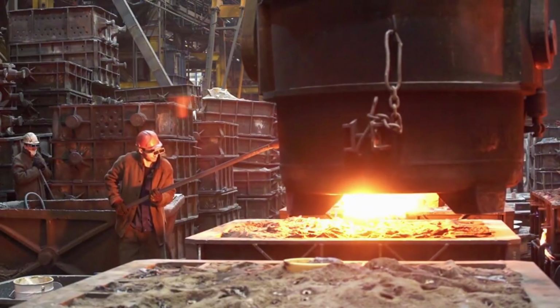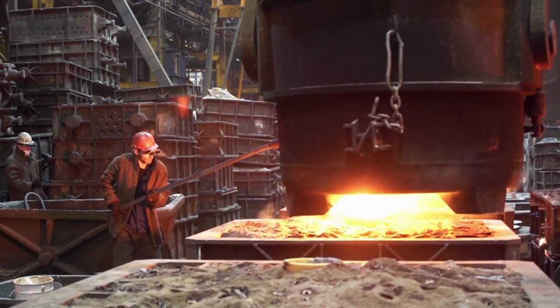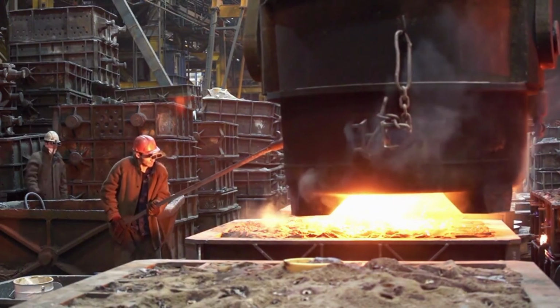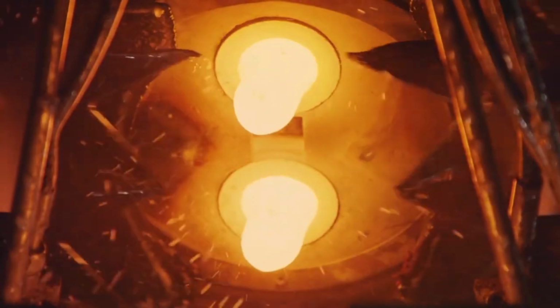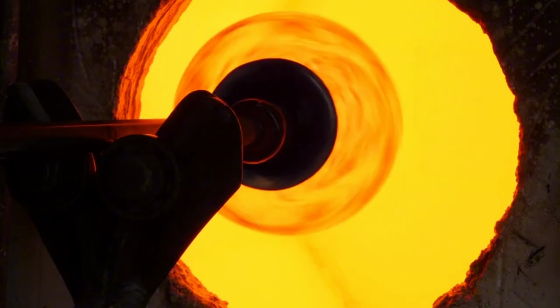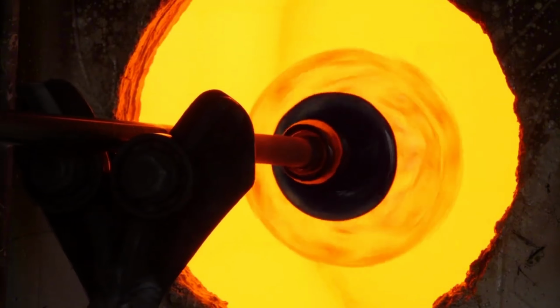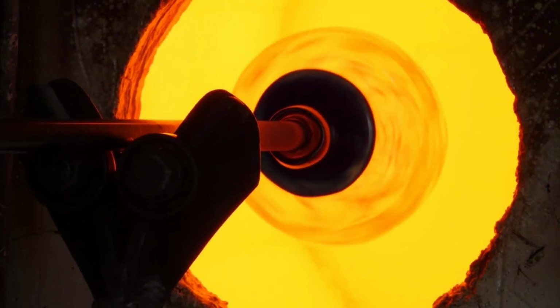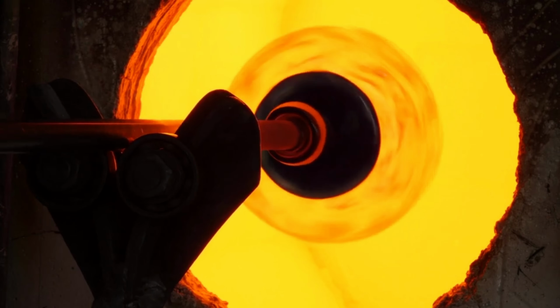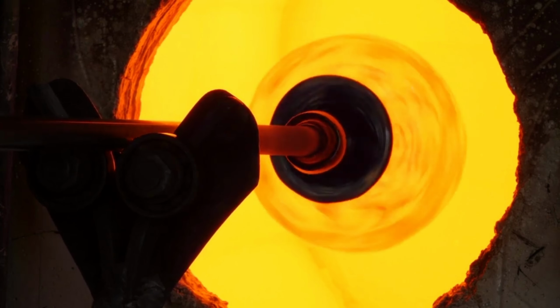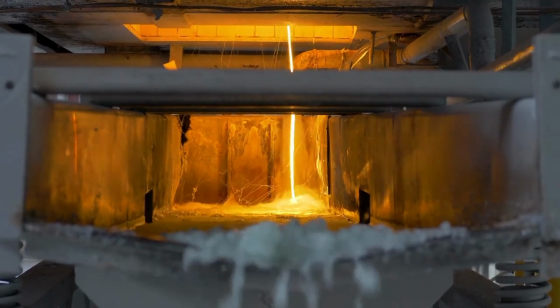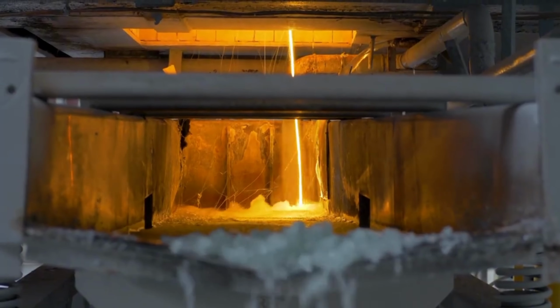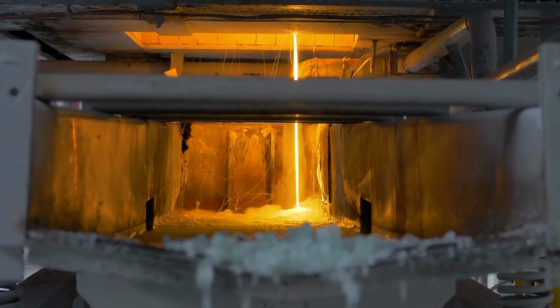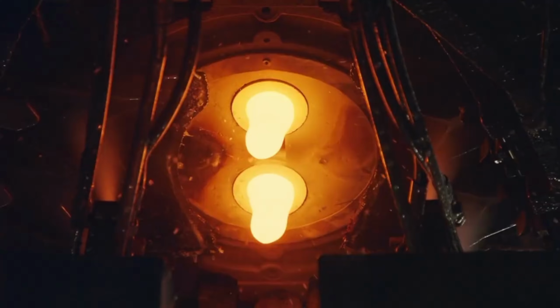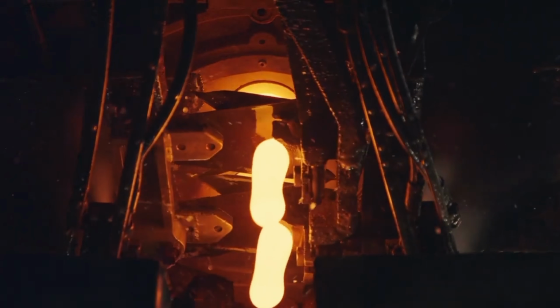After molten refinement, the blazing river of glass flows toward the Forehearth, a long temperature-controlled channel where the molten stream cools slightly from furnace temperatures but must remain at the perfect forming heat, usually between 1,100 and 1,300 degrees Celsius, creating a thick, well-conditioned, molten ribbon that will soon be sliced into precisely measured portions known as gobs, molten droplets of glowing glass the size of small apples that are cut by mechanical shears synchronized to the millisecond.